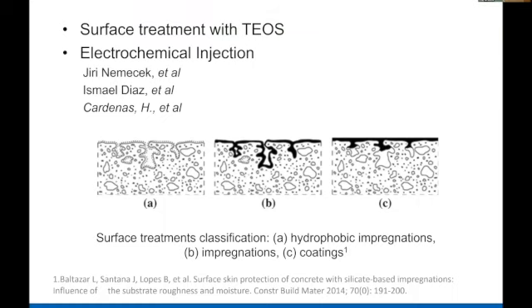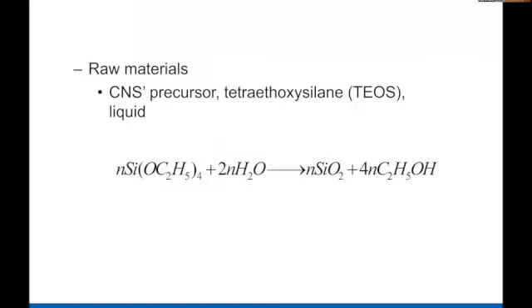So we said, okay, why not try to see whether nanosilica can penetrate the pores and react as a pozzolanic material. So we started with TEOS, which is a precursor of nanosilica. And after hydrolysis with water, it deposits nanosilica. And the last item shown here is alcohol, which evaporates.